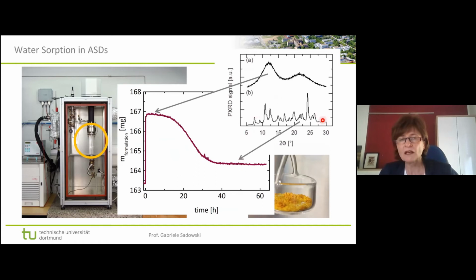crystalline. And that makes sense, because if you have the water in the system, the API doesn't want to be dissolved anymore. So it's much more supersaturated than before. So it starts crystallizing, and crystallizing takes a while. And then, the more crystals you have, the less water can be absorbed, because crystals do not absorb water. This is only absorbed by the amorphous environment. And that means water is released again. So what we see is release of water, and this at the same time means growing crystals. So we can really observe crystals growing simply by weighing the sample.